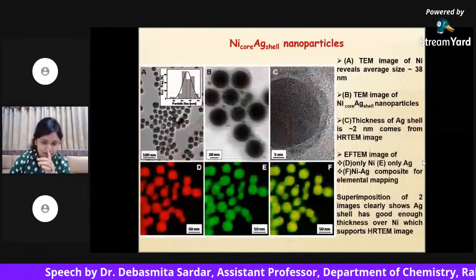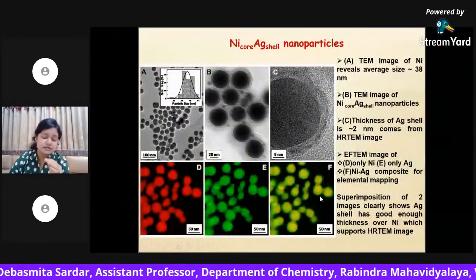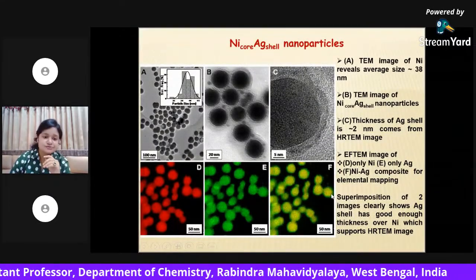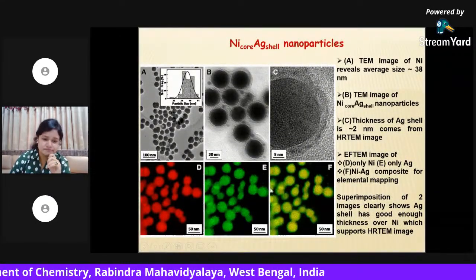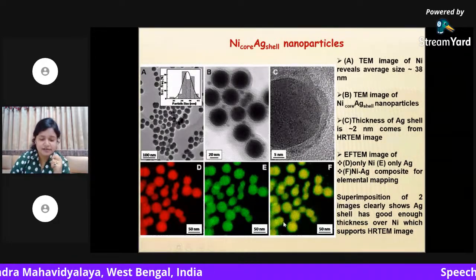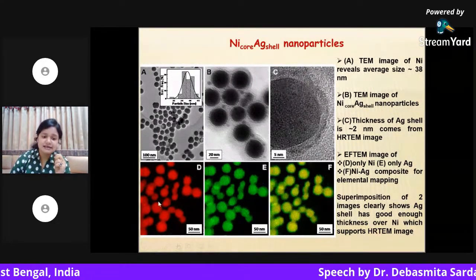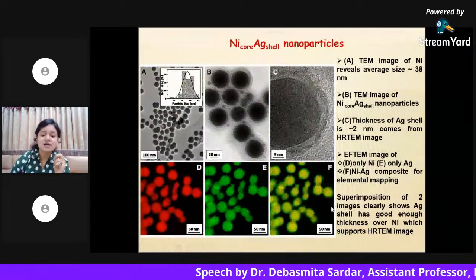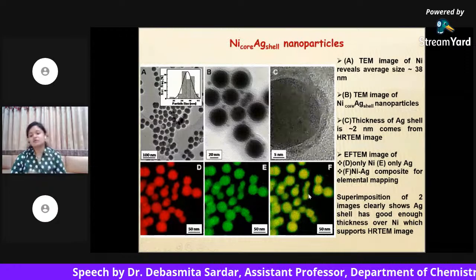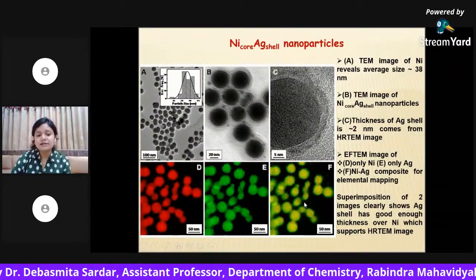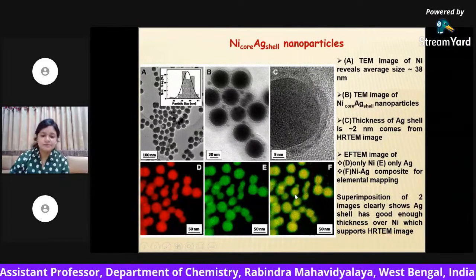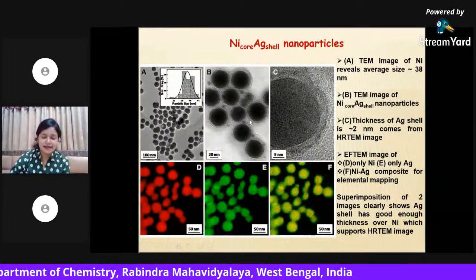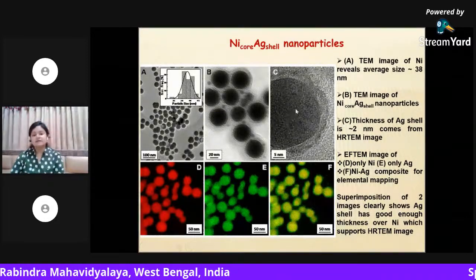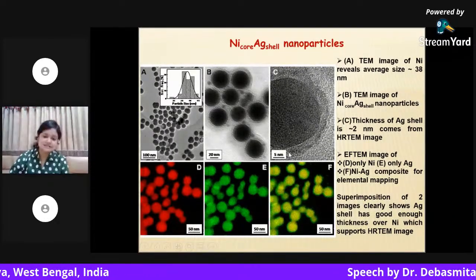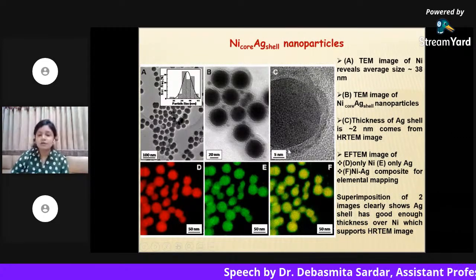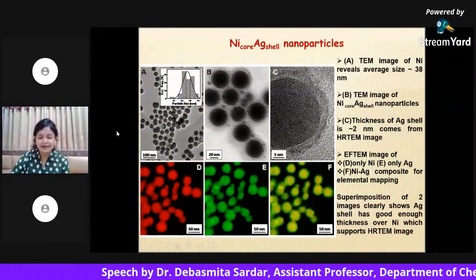Now this is nickel silver nanoparticles, the real picture. It can be seen by TEM, transmission electron microscopy. The red one is nickel and the green one is silver, and F is the composite picture where the red one and green one have been merged. And the C picture is one black nanoparticle, and you can see that there is a shell outside the black nickel nanoparticle.